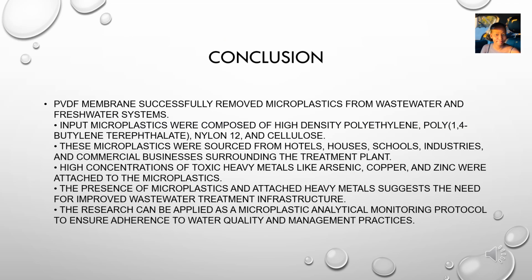In conclusion, the PVDF membrane successfully removed microplastics from wastewater and freshwater systems. The input microplastics were composed of high-density polyethylene, poly(1,4-butylene terephthalate), nylon 12, and cellulose. These microplastics were sourced from hotels, houses, schools, industries, and commercial businesses surrounding the treatment plant. High concentrations of toxic heavy metals like arsenic, copper, and zinc were attached to the microplastics.